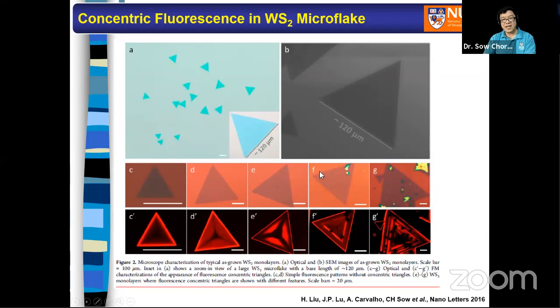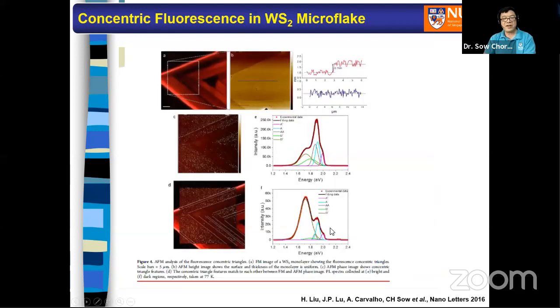The row of C, D, E, F, G tells you the optical microscope picture of how it looks. You just look at it, it looks like a triangle, nothing spectacular. However, when you look at it under fluorescent microscope mode, excited, they all give out red color fluorescence, and then amazingly, hidden within the triangle, we didn't know that there are so many detailed patterns, concentric triangles, okay? So we did a detailed investigation and found that this is due to different amounts of sulfur. We grow WS2, we think, okay? But actually it turns out that in some regions we grow WS1.98, in some regions we grow WS1.85.